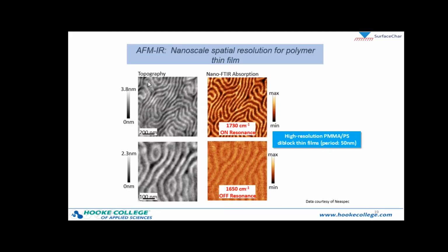Another example for polymer material application is an AFM-IR image of a diblock thin film. So this diblock was PMMA and polystyrene. We can see the topography image here. And then the IR absorption image at 1730 wave numbers, where you can now easily distinguish these two components, where one's absorbing a lot and the other not so much at this peak, which would enable unambiguous identification of which component is PMMA and which one's polystyrene.